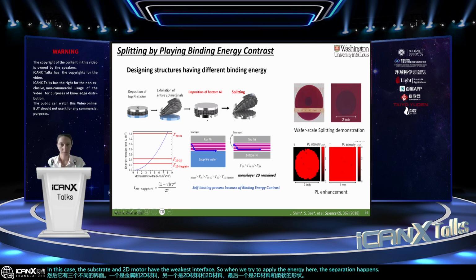Afterward, we deposit another metal at the backside. Then these two interfaces have very strong adhesion energy. So when the crack propagates, it naturally goes over this monolayer because these two interfaces have very strong interface toughness. So it's a self-limiting process, and eventually we can produce the monolayer by using this technique.